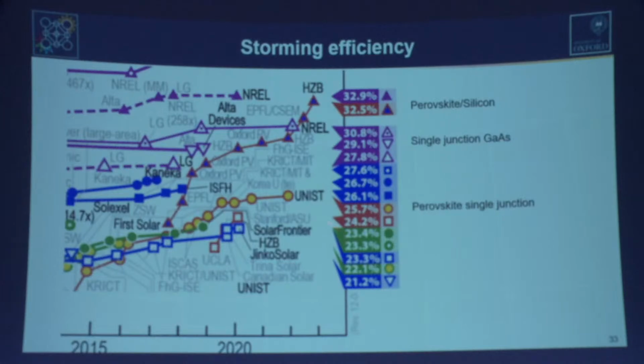So the efficiency's storming up. There's a massive increase. This is an excerpt from the National Renewable Energy Laboratory's efficiency chart. And what we can see is the perovskite on silicon tandem cells are now up at 32.5% efficiency. So actually, we're going to have to revise our calculation. I think we're going to very rapidly get to 34 and have to reassess whether we can go any higher there. And the single junction perovskites, just a single layer, is already up very close to 26% efficiency. So power efficiency is there.